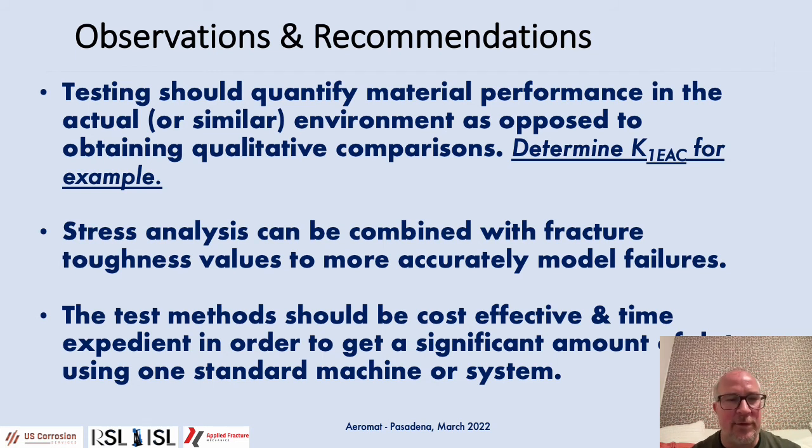So ultimately, I believe that the testing should really quantify what the material performance is, and it should be done in actual or similar environments instead of just obtaining a qualitative comparison. So for example, using step loading, you can determine the K1 EAC value for fracture toughness, and that can be used to really accurately do design of your materials.